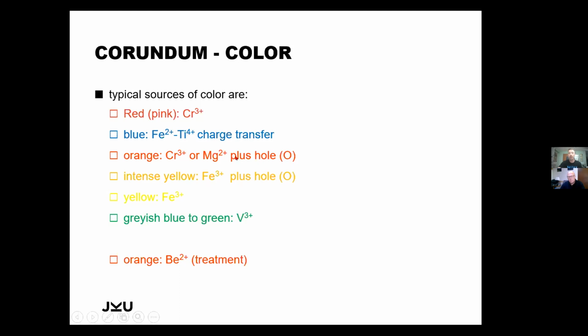And here we talk about holes, oxygen. The background is we have magnesium 2 plus sitting on the place of an aluminum 3 plus. So in order to be electrically neutral, we need to change the charge of the oxygen from 2 minus to 1 minus. And if we have a 1 minus, we have a single electron on the oxygen. And this is also a very potent light absorber. So the oxygen hole is responsible for a lot of color that is going on in sapphires. And together with the magnesium, it produces intense orange color. Intense yellows can be found when we see iron 3 plus with these oxygen holes. If we only have the iron 3 plus, we have pale to medium yellows.